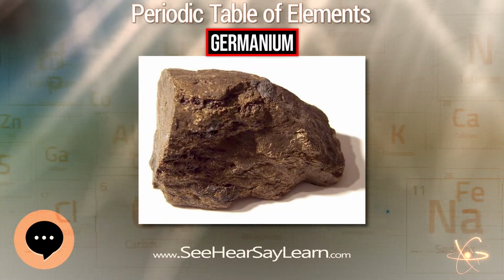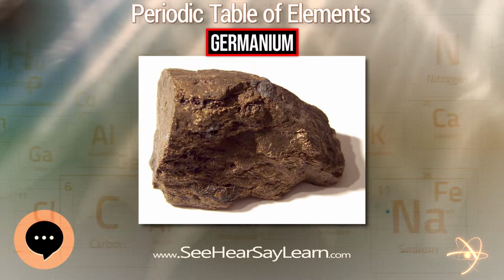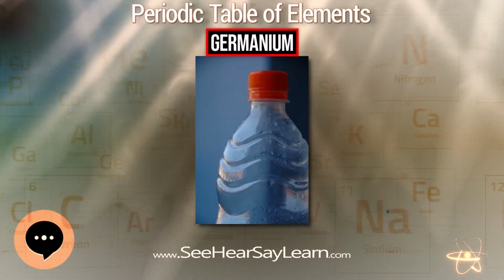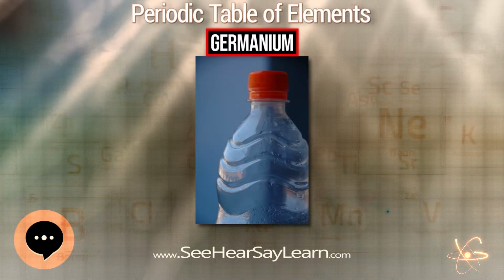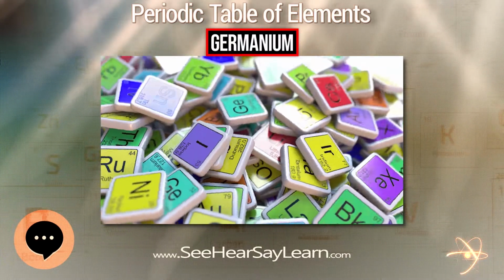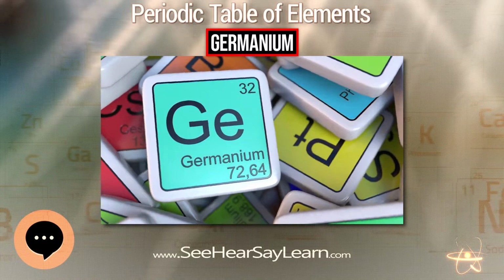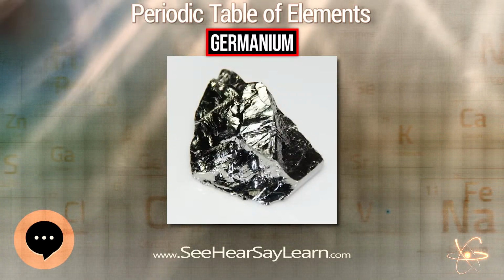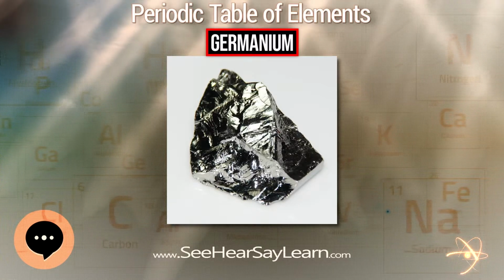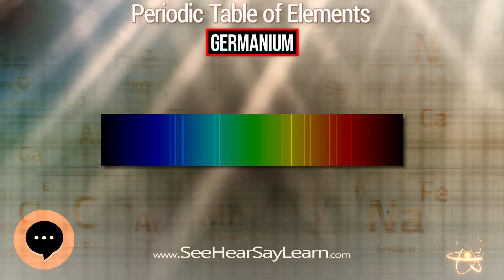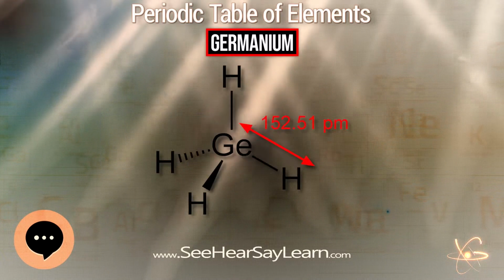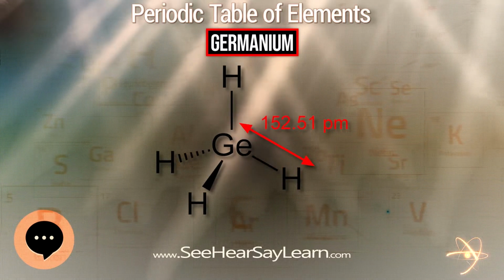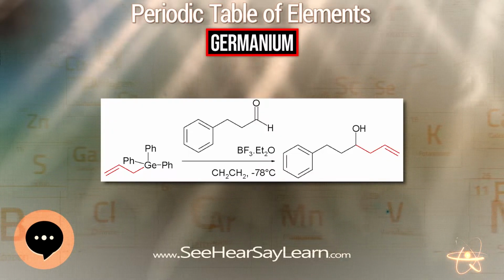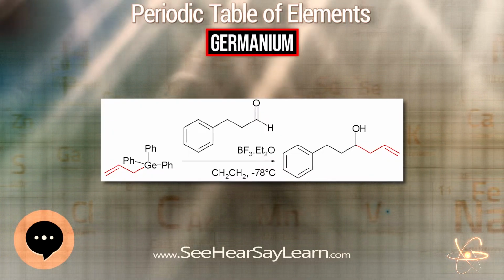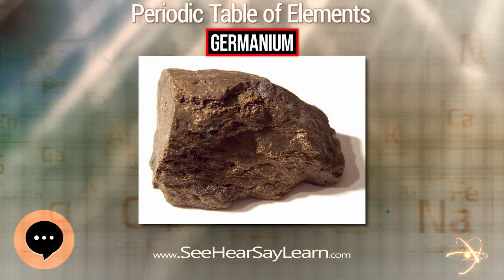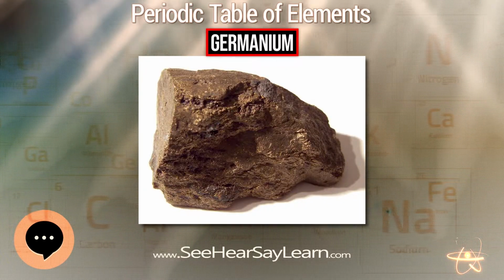The highest concentration ever found was in Hartley coal ash with as much as 1.6% germanium. The coal deposits near Lincang, Yunnan, contain an estimated 1,600 tons of germanium. About 118 tons of germanium was produced in 2011 worldwide, mostly in China, Russia, and the United States. Germanium is recovered as a byproduct from sphalerite zinc ores where it is concentrated in amounts as great as 0.3%, especially from low-temperature sediment-hosted, massive Zn-Pb-Cu deposits and carbonate-hosted Zn-Pb deposits.